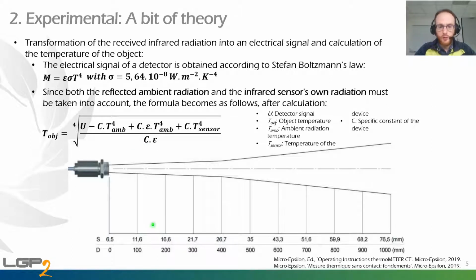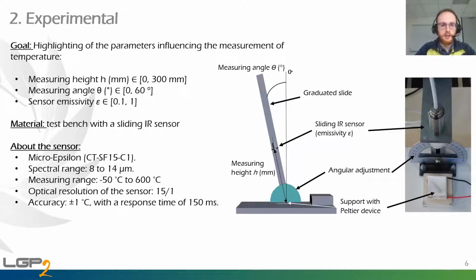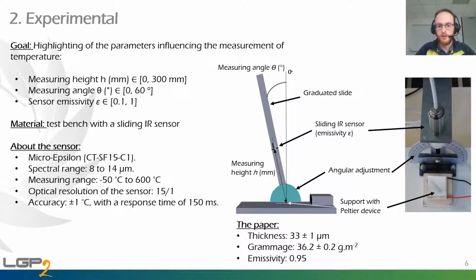The measurement shape is a cone shape, which will evolve when the distance between the sensor and an object increases or decreases. Then, concerning the highlighting of the parameters influencing the measurement of temperatures, the measurement height, angle, and emissivity will vary between these values. On the test bench, there is a sliding sensor that could go up and down, and that can vary the angle. About the sensor, it's a micro-epsilon sensor with a measuring range between minus 50 Celsius degrees to 600 Celsius degrees, with an accuracy of plus or minus 1 Celsius degree. Our paper is a very thin and light paper with an emissivity set to 0.95.